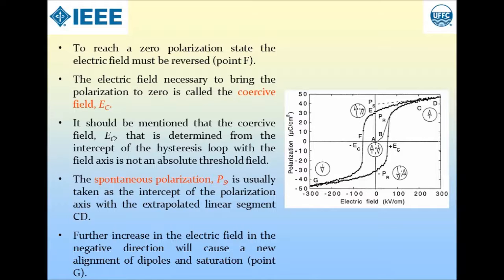It should be mentioned that the coercive field, E subscript C, that is determined from the intercept of the hysteresis loop with the field axis is not an absolute threshold field. The spontaneous polarization, P subscript S, is usually taken as the intercept of the polarization axis with the extrapolated linear segment CD. Further increase in the electric field in the negative direction will cause a new alignment of dipoles and saturation. This can be seen at point G.